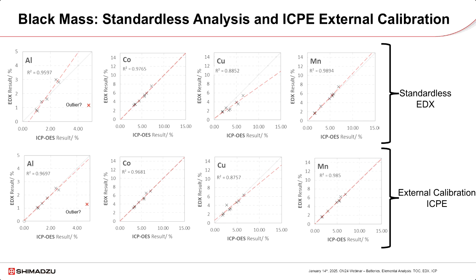For example, in the top left, we have a correlation graph for aluminum. On the x-axis is the ICP result, and then the y-axis is the EDX result without calibrating using the ICP data. For example, in the aluminum graph, you can note that the highest concentration aluminum is nominally 3% as detected by EDX, and it's nominally 2.4 to 2.2% for the ICP. Again, as I mentioned previously, EDX can be used to get an idea behind the nominal composition of your sample without standards, a process called semi-quantification, semi-quantitative.